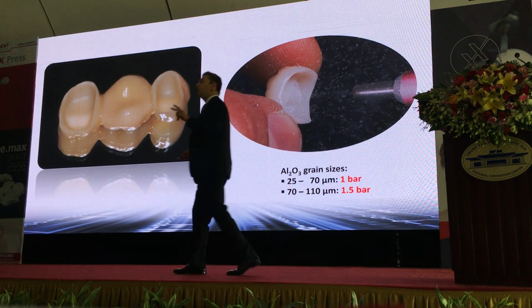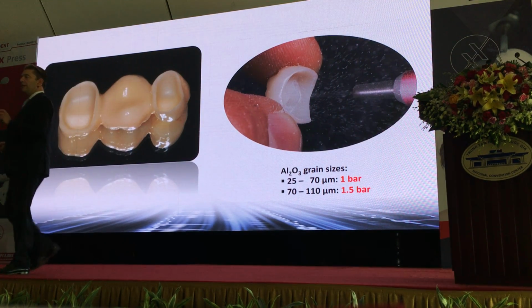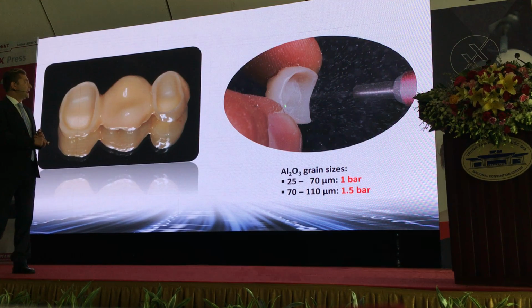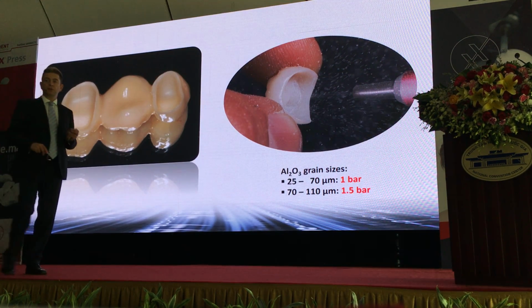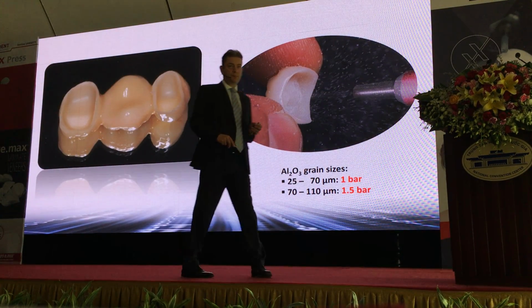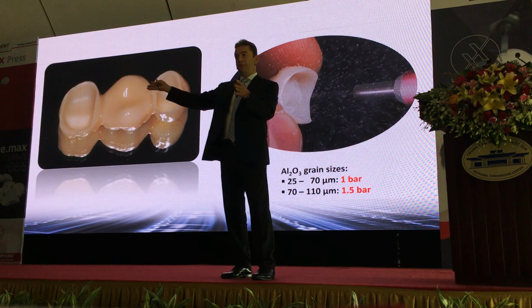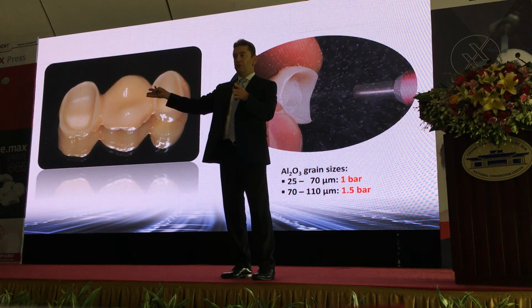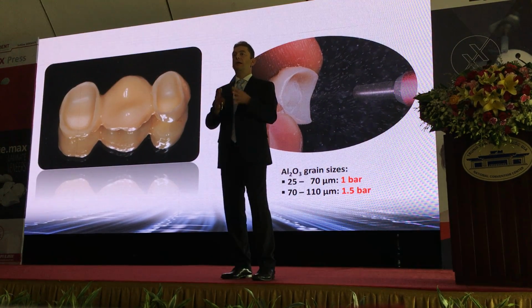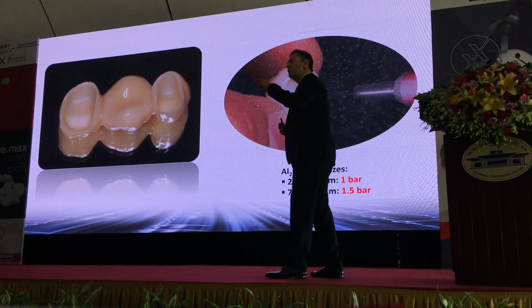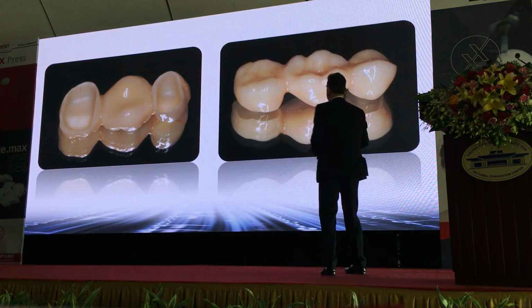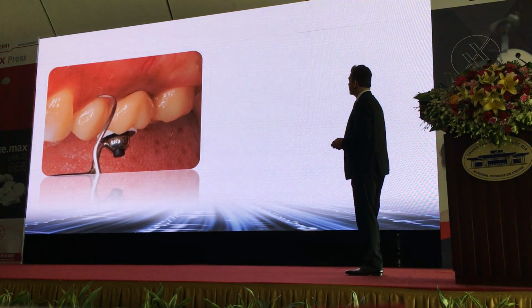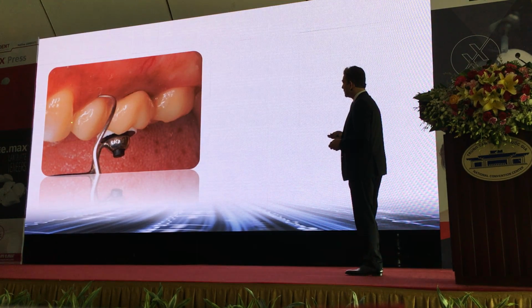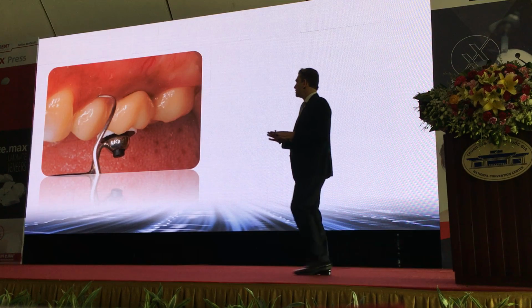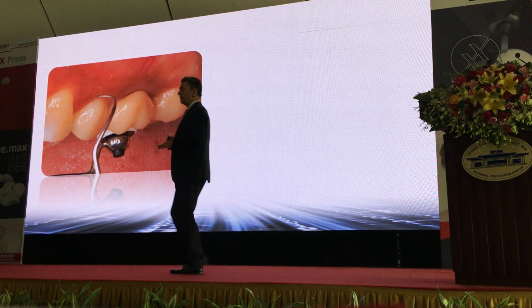Okay, so this one is ready for cementation, but the cementation of zirconia is not so easy. It always requires the zirconia to be sandblasted. So before we do the cementation of zirconia, we need to sandblast it. If you receive your zirconia from the lab, they can sandblast it. So you will receive the sandblasted zirconium oxide restoration, and now you can do a try-in. So this is the restoration. We do a try-in because you need to check the contact points, the occlusion and the articulation, and also the fit of your restoration.